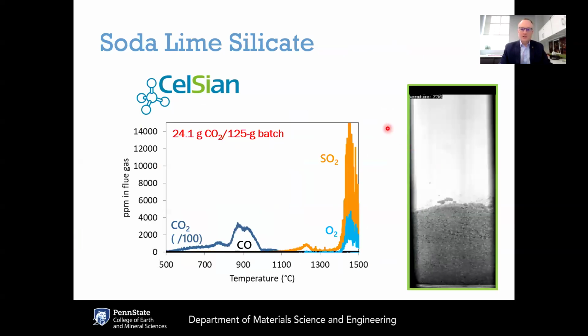And we looked at this to try to do back-to-back comparisons between a standard soda lime silicate and a LionGlass composition. This slide shows on the left the gas chromatography results as a function of temperature as the batch is heated up. And on the right, this shows a movie of the soda lime batch as it's heated up and eventually melted.